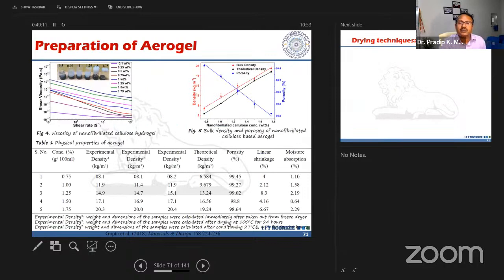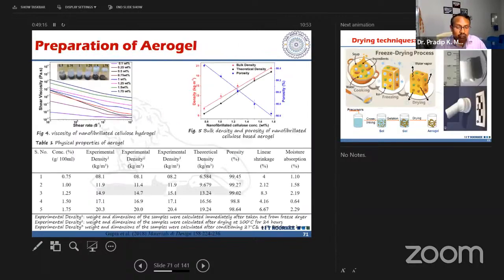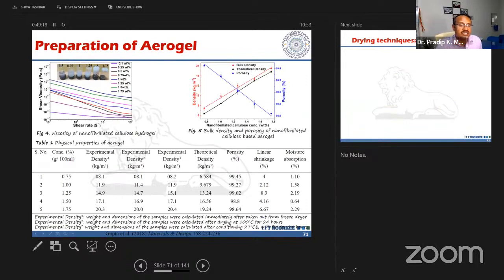Let's start with the preparation process of the cellulose aerogel. We have used different solution processes, and here we have taken different concentrations of cellulose in water: 0.7, 1, 1.2, 1.5, 1.75. We have checked the density versus porosity. Porosity started at 98.6 and ended at 99.4, so almost all of it is air, with only a small amount of material, and the bulk density and theoretical density are again very, very less.